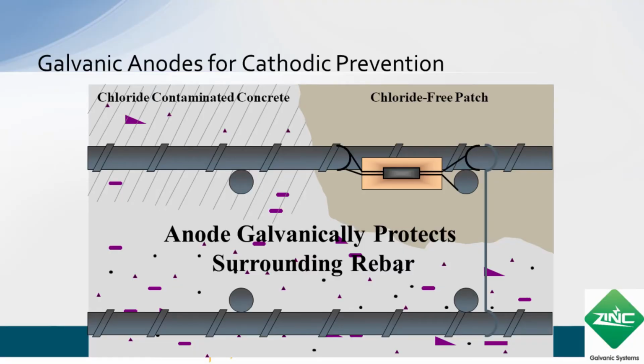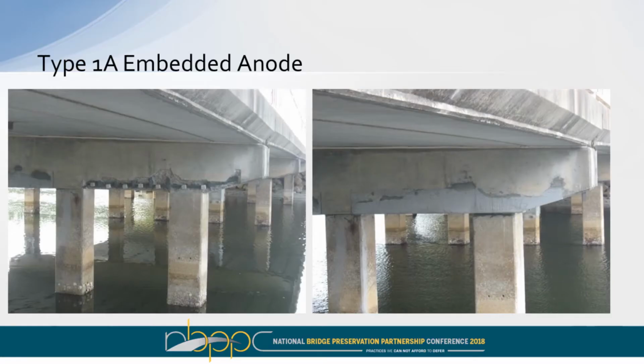So in many cases, you're leaving behind chloride contaminated concrete, even if you follow good concrete repair procedures like we saw with ICRI. So in this case, these are an application potentially where you can look at using embedded galvanic anodes. In this case, this is just an illustration of a type 1 embedded galvanic anode connected to the reinforcing steel at the edge of a concrete patch repair.